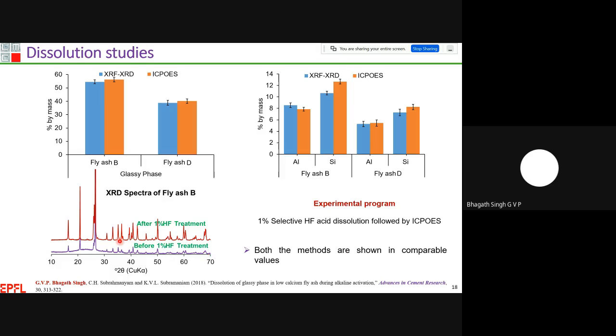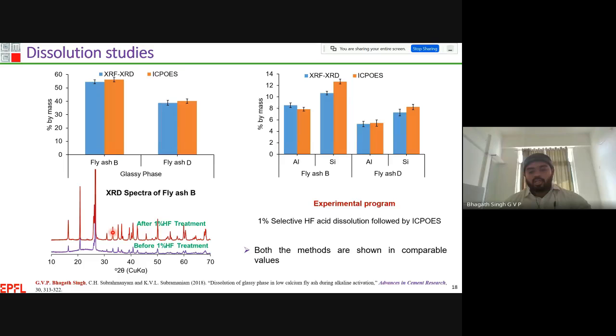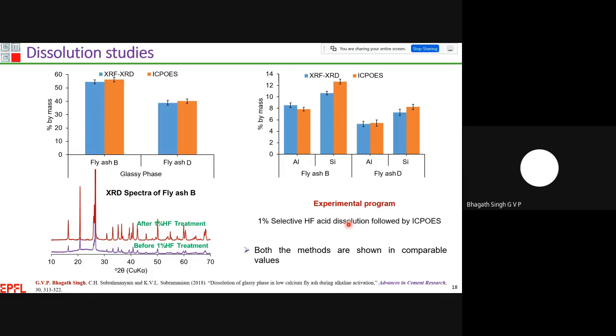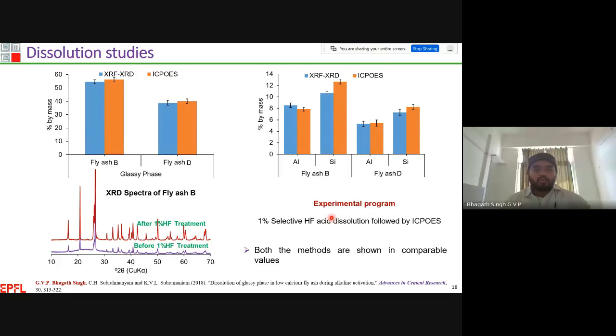And as you can see here, this is the XRD spectra before HF treatment. After HF treatment, the whole amorphous portion is completely dissolved without affecting the crystalline phases, which means that the HF acid dissolution dissolves only the glassy portion, not the crystalline phases. But this treatment is very sensitive to time. We have to restrict the time while we're doing this methodology. If you exceed your time limit, then it will dissolve some of your crystalline phases as well.